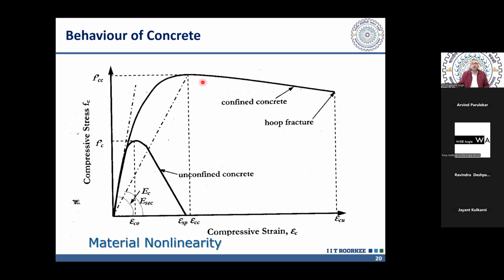But when we confine the concrete, I'm not going into the detail of how unconfined and confined concrete behave, but you can see this in any book. When we confine the concrete, its strength increases and its ductility. That means the strain range in which the material behaves inelastically increases tremendously. So you can see that confined concrete stress strain behavior is like this. Unconfined concrete is very brittle. Confined concrete becomes somewhat ductile, but still not as ductile as the steel because this ultimate strain is of the order of 0.02, 2%. Whereas in case of steel, it is of the order of 20% ultimate strain.